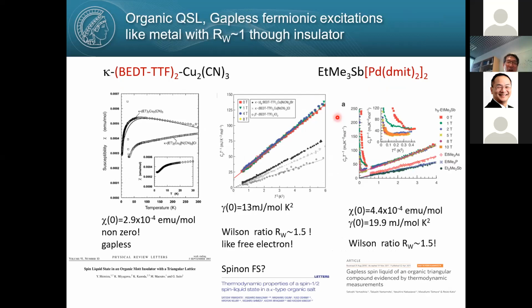And here is magnetic susceptibility. And you can see Curie-Weiss behavior, increasing with decreasing temperature at high temperature, but no anomaly representing antiferromagnetic ordering. Here is specific heat. You don't see any lambda-type anomaly representing magnetic ordering.